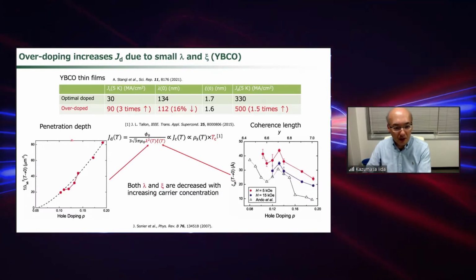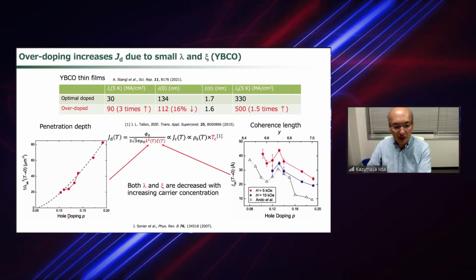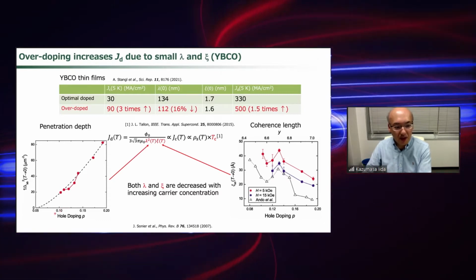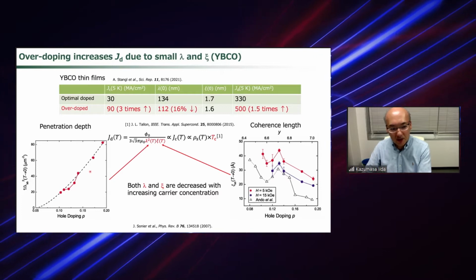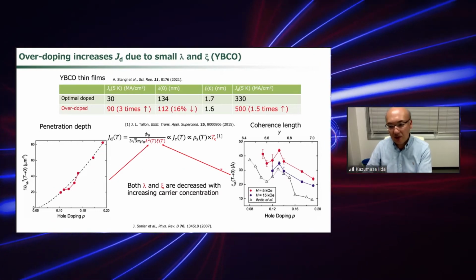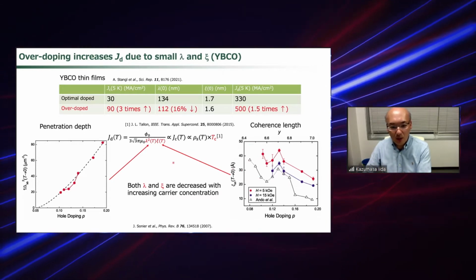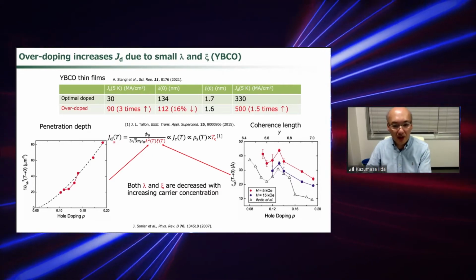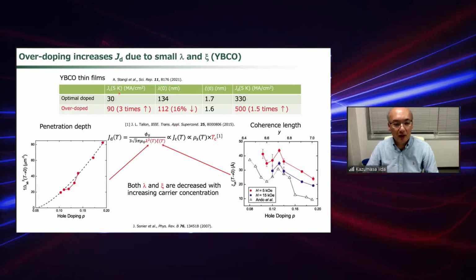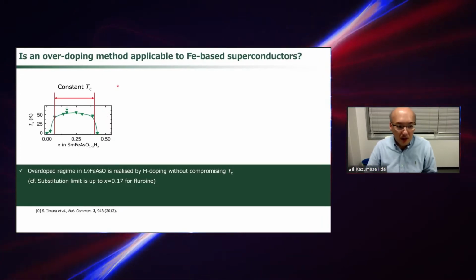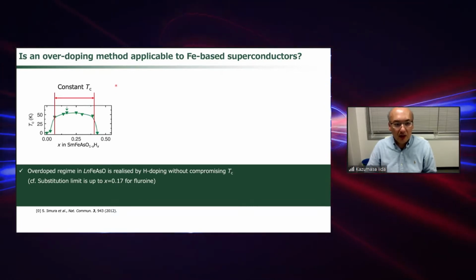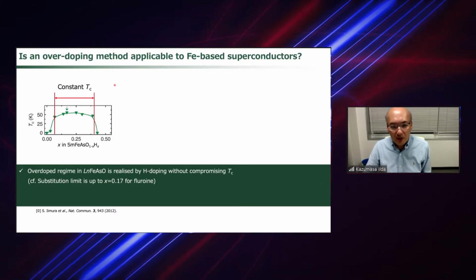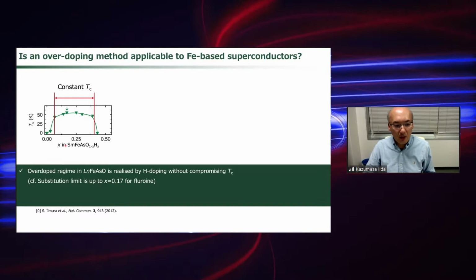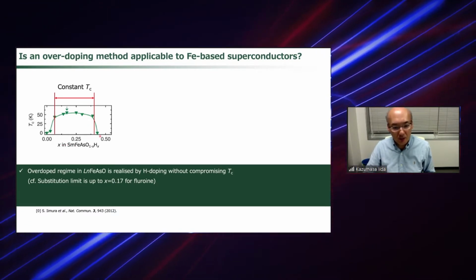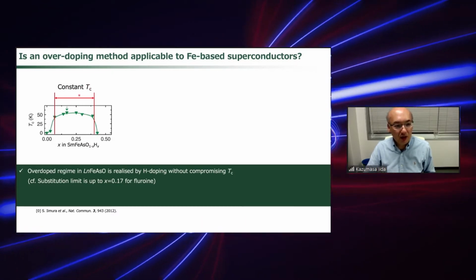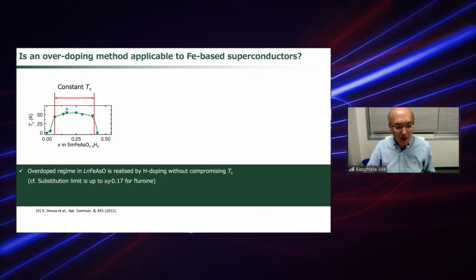Here is the penetration depth and the coherence length of YBCO as a function of the hole doping concentration. As you can see, with increasing hole concentration, the inverse of the penetration depth increases, and the coherence length decreases. That is the reason the overdoping method improves the depairing current density, which leads to the improved self-field critical current density of these materials. With this in mind, we employ this method for the iron-based superconductors. The 1111 system is our choice of material because overdoping is realized by hydrogen doping without compromising the superconducting transition temperature. And here is the fluorine doping.